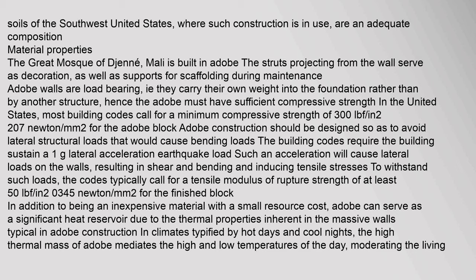The Great Mosque of Djenné, Mali, is built in adobe. The struts projecting from the wall serve as decoration as well as supports for scaffolding during maintenance. Adobe walls are load-bearing, meaning they carry their own weight into the foundation rather than by another structure, and hence the adobe must have sufficient compressive strength. In the United States, most building codes call for a minimum compressive strength of 300 psi.